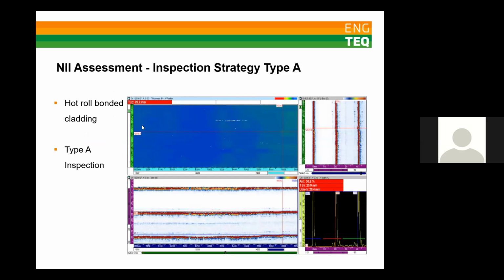So this is really what you might expect to see in the inspection results for a type A inspection. And in this case, this is a hot roll bond cladded vessel. So this is a carbon steel vessel that's internally lined with corrosion resistant alloy. And the hot roll bond cladding are the most common types, where the stainless steel and the carbon steel are fused together by rolling at temperature in the mill, and then the clad plate produced is then used to fabricate the vessels.